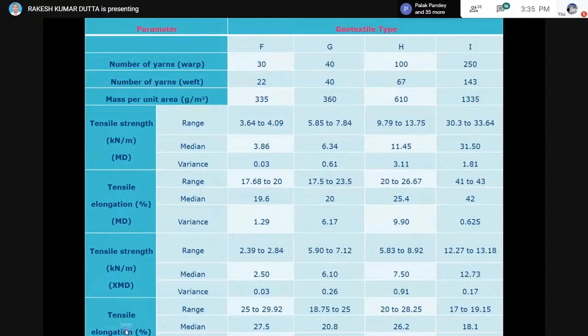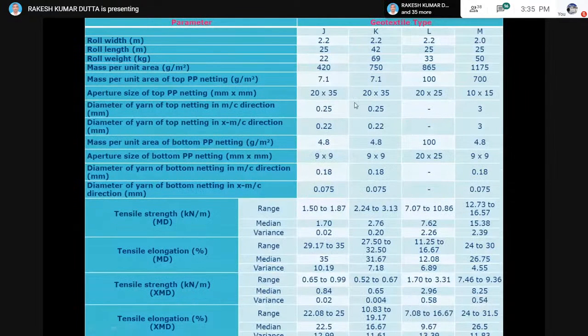Now if we take the case of a non-woven geotextile, so this is all related to the non-woven geotextile. So roll length, roll width, mass per unit area. This is true in this case also. Larger the mass per unit area, larger is going to be the strength. But the strength, if you see, it is 15, 7, 2, and approximately 1.7 in the machine direction. So now we'll see for what reason we are getting lesser strength for the first material.